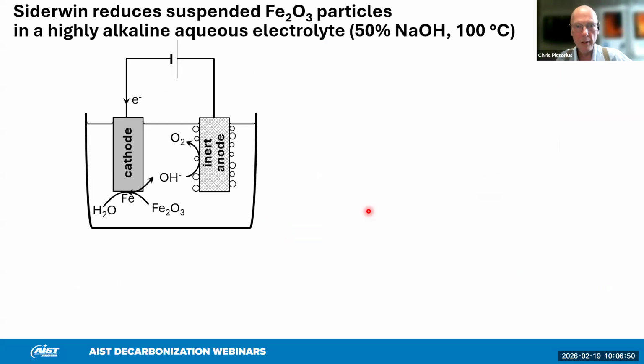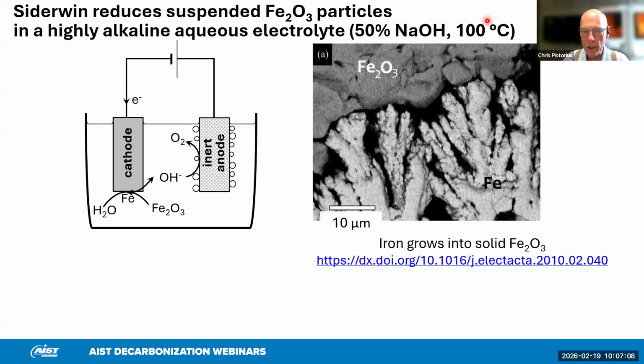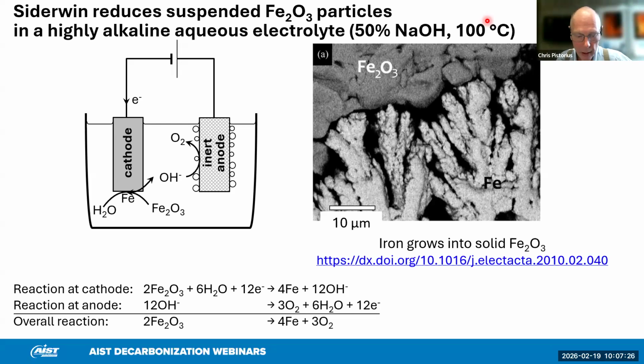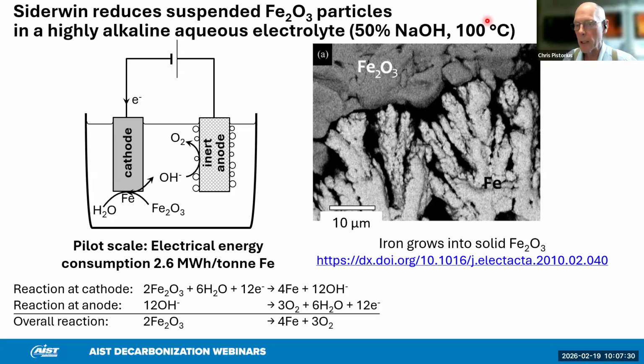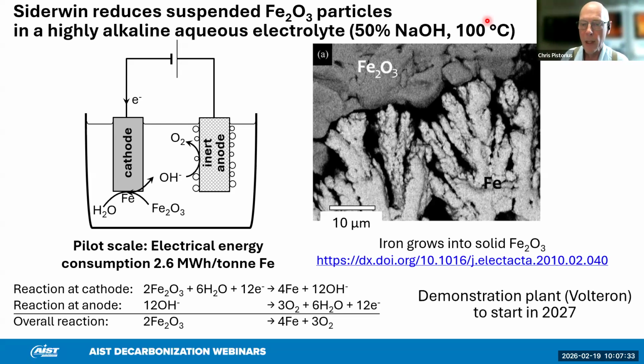There are a couple of low temperature processes that I'll briefly mention. There's one that was developed as part of the European ULCOS program, Siderwin, which runs at modest temperatures, 100 degrees Celsius, very alkaline solution. The iron stays solid. So interestingly, this is a solid state reduction process where the iron grows as these dendritic growths into the existing iron oxide. So any gangue, of course, will be kept in the material. And it's run at numbers like 2.6 megawatt hours per ton of iron at large lab scale. And this is about to be demonstrated in a plant called Volteron that is due to start next year.